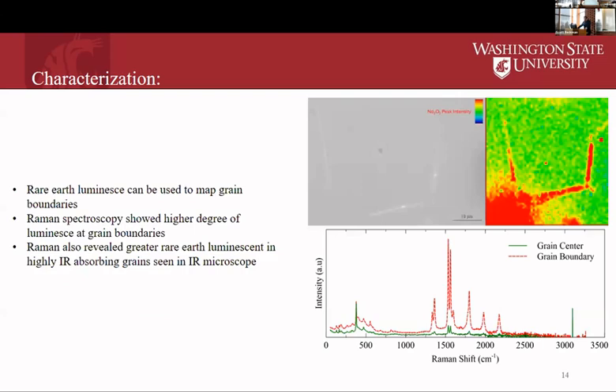One of the interesting things we were also able to do is track the rare earth luminescence in our samples. We were actually able to see our grain boundaries based on the rare earth luminescence. Right here we have a kind of highly visible grain boundary that you can see.